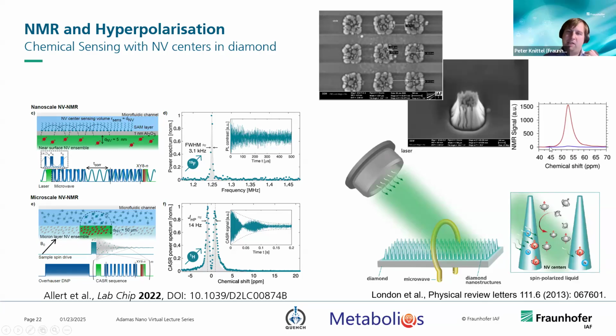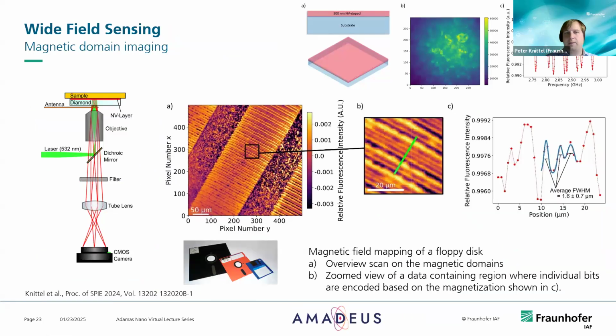And especially in MRI, it can even allow you to get information on the species that is detected. So it allows you maybe even to detect metabolic products in an MRI scan. So this is where especially very thin layers and maybe structured layers come into play. So you need a large surface area to transfer as much polarization to the liquid as possible. Another straightforward approach is just using this magnetic field sensitivity to sense magnetic fields in close proximity to NV centers. And for that, we use these nanometer-sized NV doped layers.